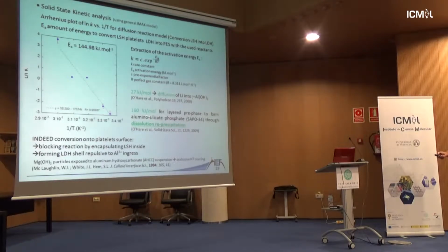If you check, in this case, the transformation from a layered precursor phase to form aluminum silicate phosphate, SAPO, which was done by the group of Professor O'Hare a few years ago, you get 160, and they justify that by a dissolution and reprecipitation. And when you think about that, of course, it can only be dissolution and reprecipitation, because if you have aluminum reacting with LSH directly, the inside layers would be completely untouched, because you would have a blocking reaction by encapsulating LDH surrounding LSH, and you would have no migration, no ingress of aluminum inside your LSH anymore.